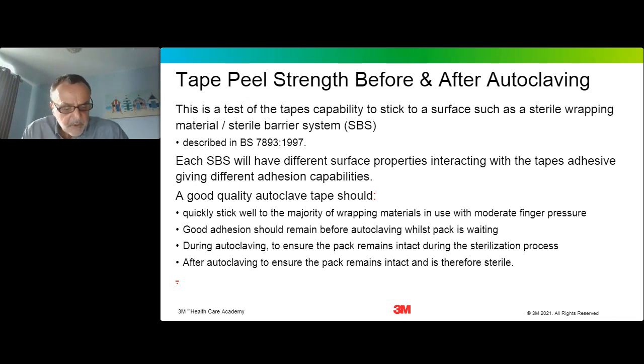The tape should also stick well and remain adherent before the pack is autoclaved, which should obviously be as quickly after application as possible, but generally it might be up from 30 minutes to an hour before the packs are sterilised. And the tape should remain adherent during the autoclaving process, so the pack remains intact, particularly during the different pressure and temperature transitions that are going to occur during the sterilisation process. And the tape should also remain adherent after sterilisation, but importantly, it should remain adherent for many months afterwards. Some of these packs will obviously be used within possibly a few hours or a day of sterilisation, but others might actually be stored on a shelf for several days, weeks, or even months before they're used. And many adhesives will age during storage periods, and that aging process should not inhibit the adhesive properties of this tape.